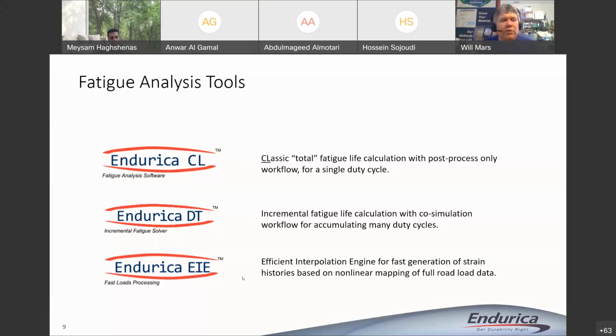EIE is a tool that we use for managing lengthy road load histories, right? And what I mean by a road load is sometimes an organization will go out to the test track and they'll make measurements of the loads that go into a part. And of course, if you're driving down a bumpy road, you're going to end up with variable amplitude data, potentially on several channels, right? Typically in a rubber part, they'll look at 6 channels. You'll have 3 forces and 3 moments that go into the part, and so they'll just make recordings at, let's say, 1,000 hertz, right? And so if you have 1,000 hertz over a half an hour event at the track, that means you've got 2 million time steps of information that you want to analyze.